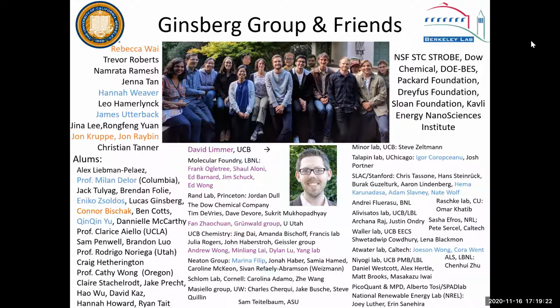So my sort of annoying question is, in 3 dimensions, the particles can't just disappear. So how much of this is analogous in, let's say, a three-dimensional colloidal system, where on one hand the particles have nowhere to go, but on the other hand the density phase transition might be less dramatic because you're in 3 dimensions, and so the entropy of melting is a little bit lower.